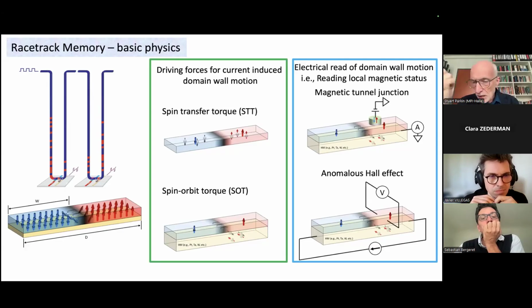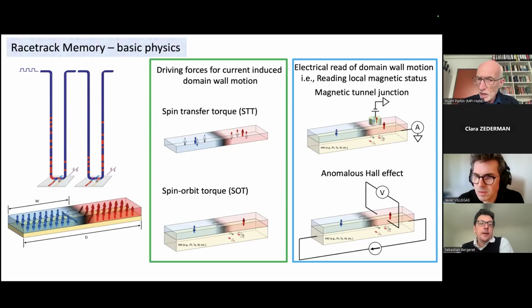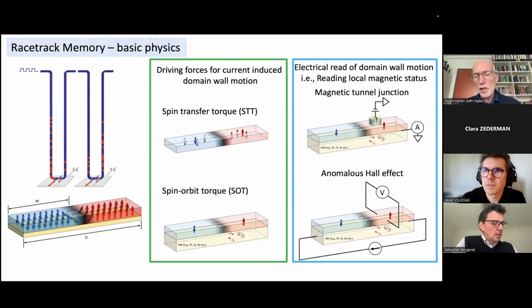Basically just a magnetic wire or magnetic film, no other layers present, the current is automatically spin polarized through spin-dependent scattering. The polarization can be up to 70% in nickel iron, nickel cobalt alloys. And when the conduction electrons, which are spin polarized, cross the domain wall, it moves. That's spin transfer torque. But around 2012, another concept arose, which is now called spin orbit